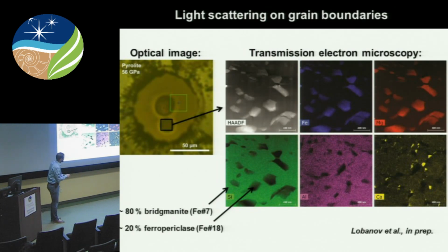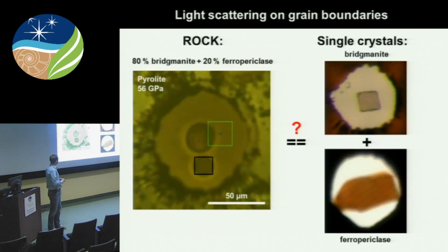So we have extracted this sample, FIB'd it, and then constructed TEM maps of its chemical composition and grain structure. So important things to note here is that our sample essentially has three minerals: bridgmanite, ferropericlase, and a little bit of calcium perovskite, just as you would expect for the pyrolitic lower mantle. But the grain size, and that's very important, is on the order of 400 nanometers. So the grain size is actually comparable to the wavelength that we're using to probe the optical properties of the sample, which means that the scattering effects might be quite substantial.